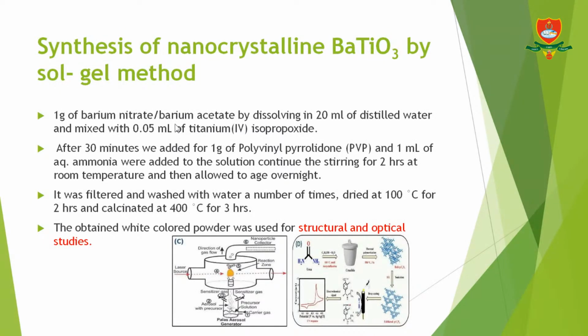Synthesis of nanocrystalline barium titanate by the sol-gel method. 1 gram of barium nitrate and barium acetate was dissolved in 20 ml of distilled water and mixed with titanium 4 isopropoxide. After stirring for 30 minutes, 1 gram of polyvinyl pyrrolidone and 1 milliliter of aqueous ammonia were added and stirring continued for 2 hours at room temperature, and then allowed to age overnight. It was filtered and washed with water a number of times, then dried and calcined. The white colored powder was obtained and it was used for structural and optical studies.